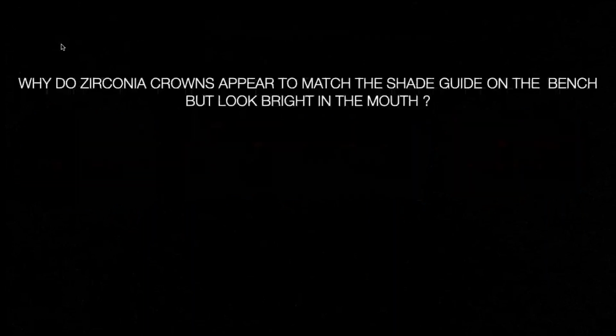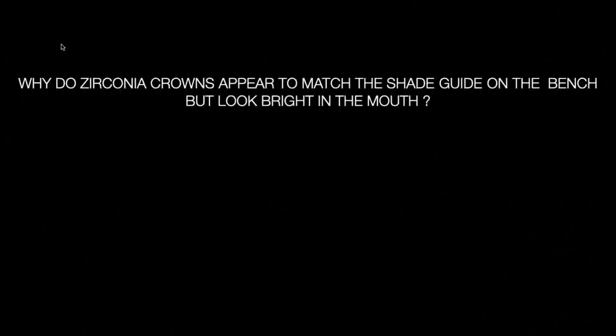Now, why do zirconia crowns appear to match a shade guide on the bench, but they look bright in the mouth? That's always been the case. Now, some 5Y zirconia actually look too gray in the mouth. And if you glaze it or have to touch the surface, you polish it, it all looks like a pearl. And a lot of people don't like that. I don't really mind it, but I layer just about everything.